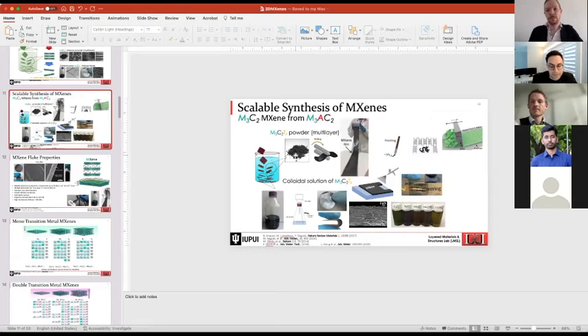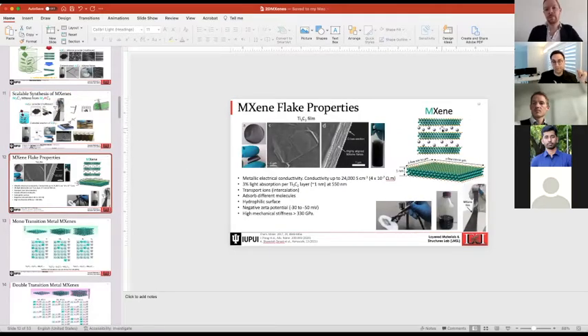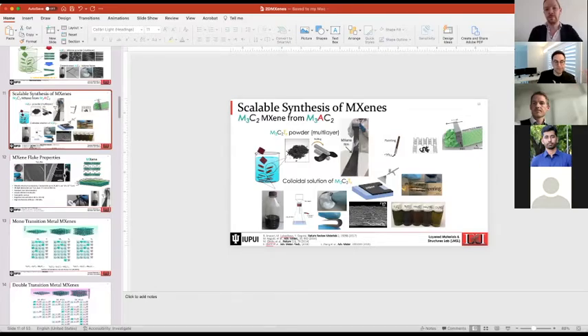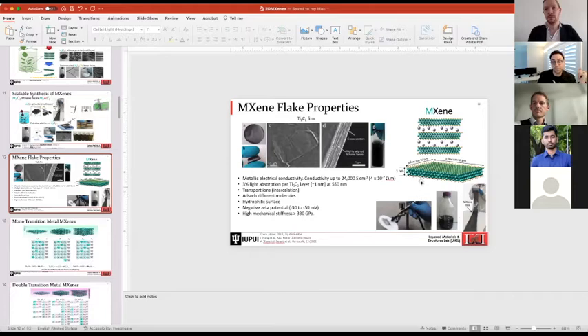Depending on the synthesis route of MXene, for example, when we use the HCl-LiF method, we create MXene clay, meaning that they can accommodate up to 3 layers of water molecules in between the layers. That basically means they can absorb water. For example, if you put it in water, it swells to a larger volume because it can have up to 3 layers of water molecules in between the layers. So they can easily absorb water in between the layers. This water absorption happens in between the layers, not on the surface. So that's why MXene clay powder will be so effective to absorb water.